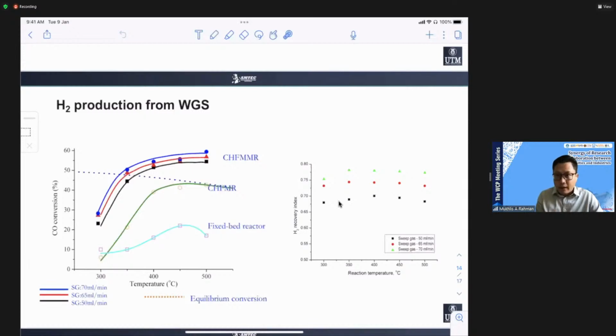However, when we put the palladium membrane on the outer surface, we can see that the equilibrium is exceeded, pushing the product formation. So the reaction now moves toward hydrogen production. In our process, we didn't use a vacuum, we use a sweeping gas. The higher the sweeping gas flow that we use, the higher the amount of hydrogen being produced.